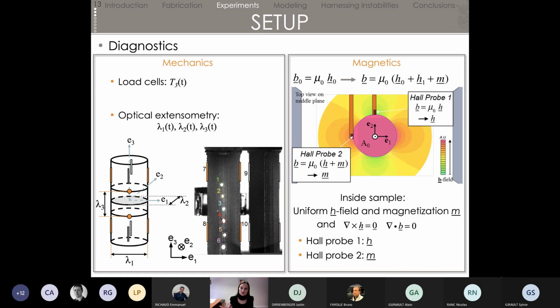So in the end, to know how the sample responds to this magnetic field, we have two quantities to measure, H1 and M. To do that, we are using the equations that are recalled here: curl of H equals 0 and divergence of B equals 0. What it tells us basically is that at the back of the sample, where you have the box with Hall probe 1, you have continuity of the tangential component of H. So that means that at this point, M vanishes. If you put your probe here, what you're measuring is H. And since we know H0, because that's what we applied, that helps us find H1.